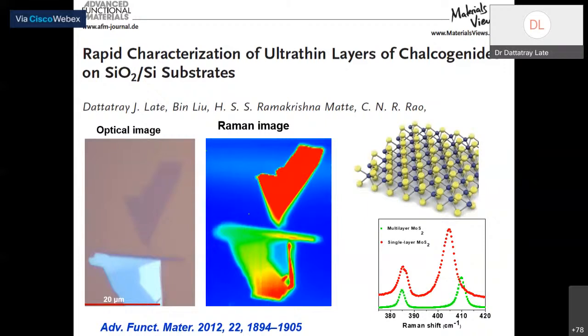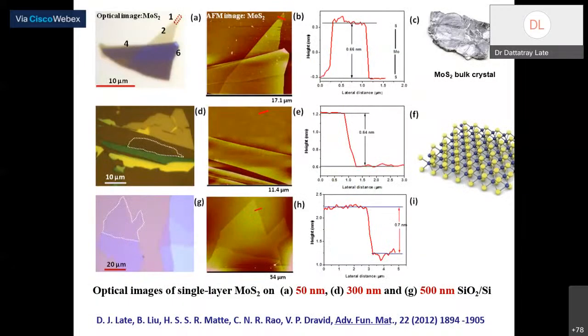So again, we need a bulk MoS2 crystal, WS2 crystal, or whatever, and I can put it on Scotch tape. Again, as mentioned, any kind of SiO2 substrate is fine. Here, I have shown you different optical images. This optical image is for MoS2 deposited on 50 nanometer of SiO2. Then this D image is for 300 nanometer of SiO2, and this G image is for 500 nanometer SiO2 on Si substrate. So MoS2 is the same everywhere. The nature is the same, like monolayer of MoS2, but the thickness of SiO2 has been changed.